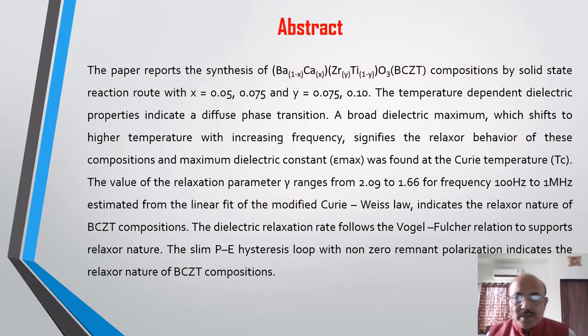The abstract of this presentation is that the paper reports the synthesis of Ba1-xCaxZryTi1-yO3, that is BCZT, compositions by solid-state reaction route with x 0.05, 0.075 and y 0.075, 0.10. The temperature-dependent dielectric properties indicate diffuse phase transition characteristics. A broad dielectric maxima that shifts to higher temperature with increasing frequency signifies the relaxor behavior of these compositions, and the maximum dielectric constant, that is epsilon max, was found at the Curie temperature Tc.